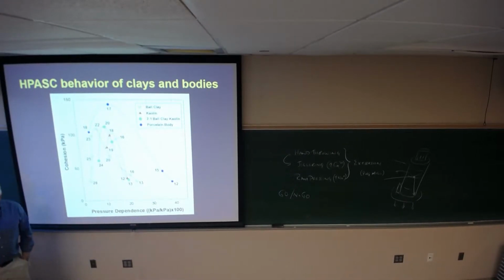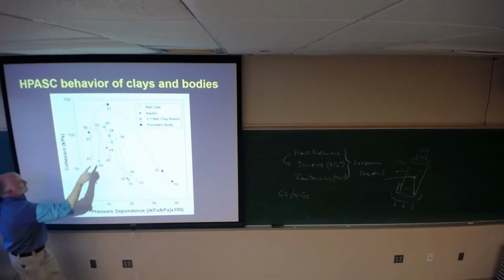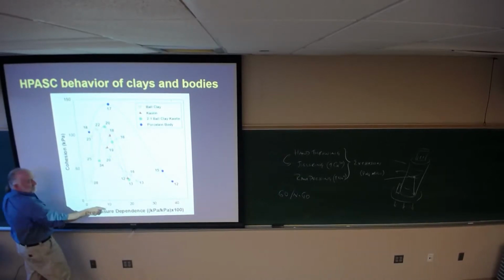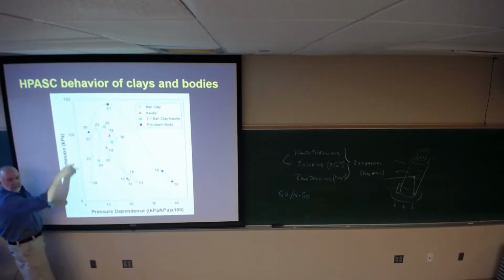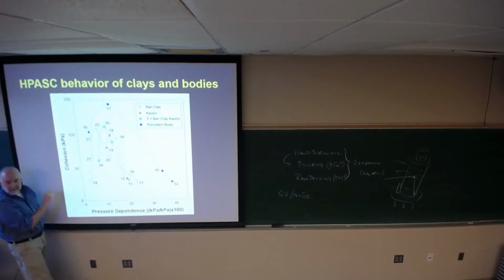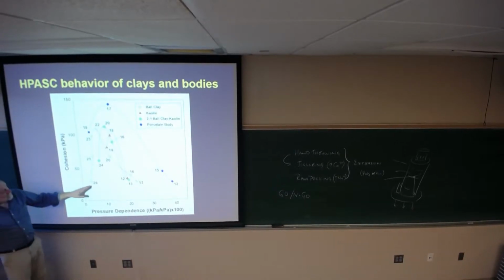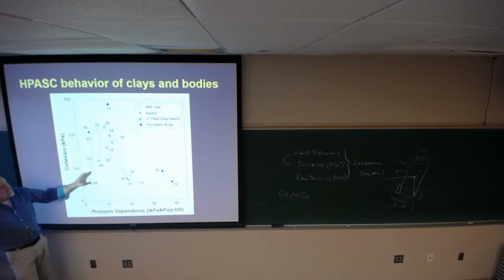Okay, and that peak that you see is right at the point of saturation, just before saturation or at saturation. And then what happens is that once you saturate, then your pressure dependence is going to 0. Your yield stress is dropped. Does this make sense? So you saturate that system. So what do you see? You see, well, kaolin and ball clay in a mixture, they require different water contents to saturate that body. Does that make sense? Okay.